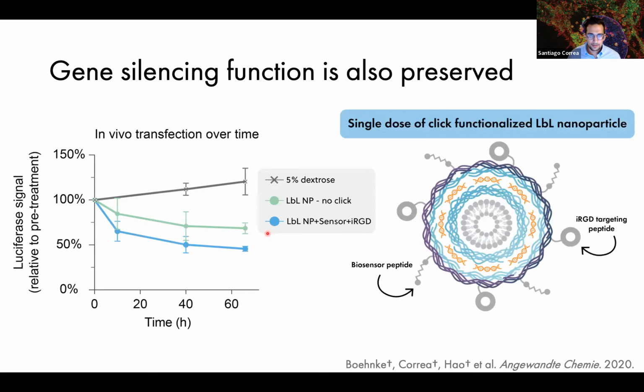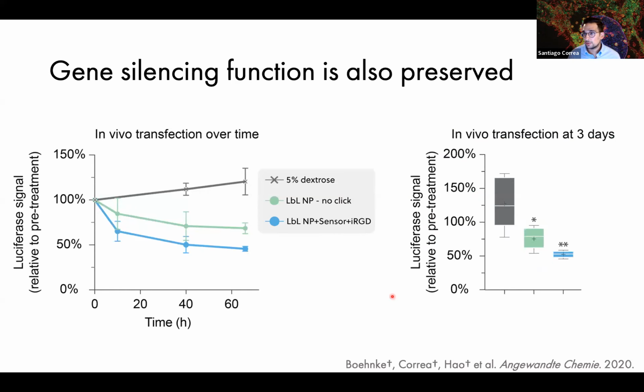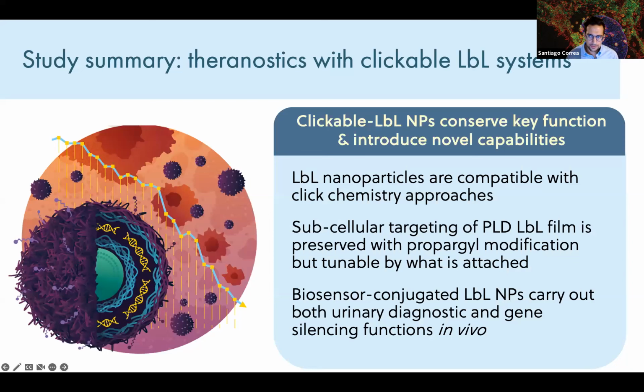But the exciting result was that when we looked at our click modified nanoparticle that has this diagnostic functionality included, we see the same overall kinetics of silencing, but we see just improved silencing across the board, which really is consistent with what we were seeing with those super resolution micrographs. And so to summarize this particular study, essentially we saw that this unique property of the polyaspartic acid coating could be leveraged to develop this theranostic platform that allowed for both gene silencing and urine-based detection of tumors.